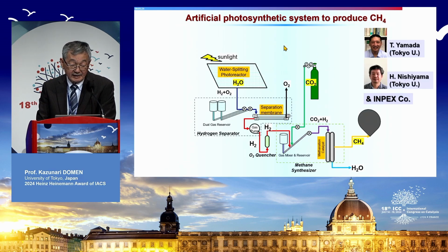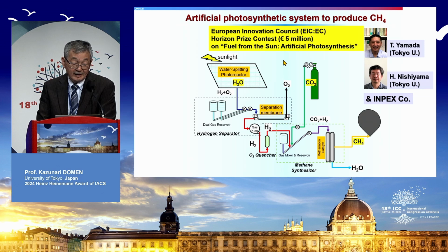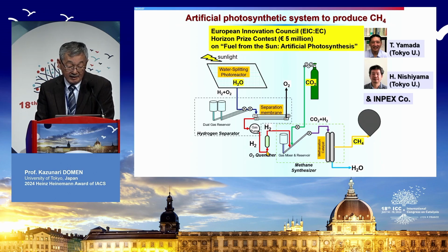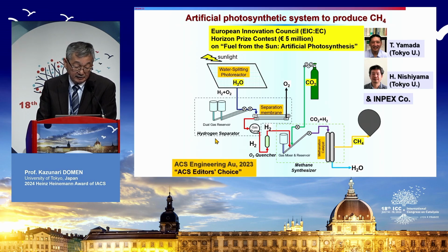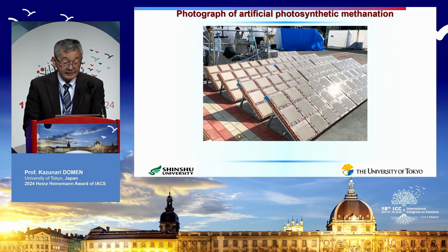And here I show the structure which we constructed for the European Innovation Council's Horizon Prize contest on fuel from the sun, artificial photosynthesis. In this case, we have a water splitting panel, and this is a gas separation membrane. After quenching our gas, we obtain pure hydrogen, and it is mixed with carbon dioxide to form methane, which works at about 200 degrees C. A more detailed structure of this system was already reported in ACS Engineering. And this is a real structure.